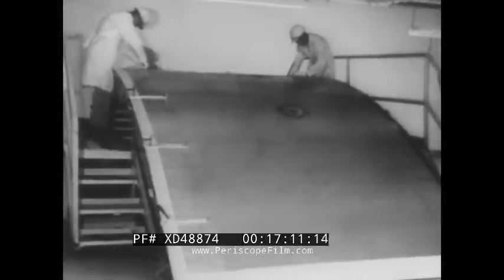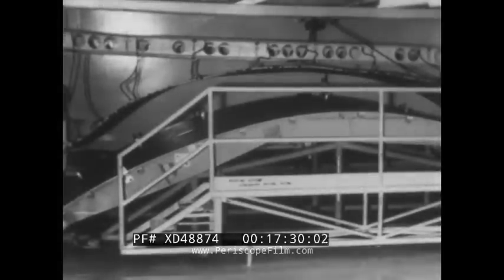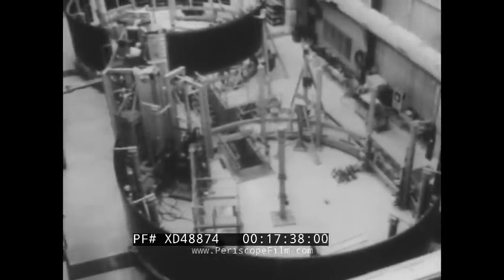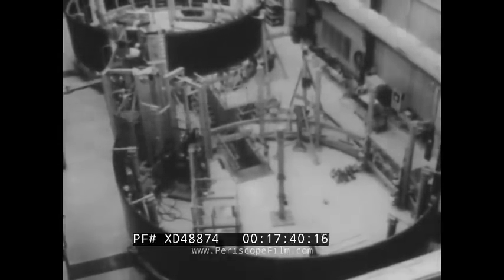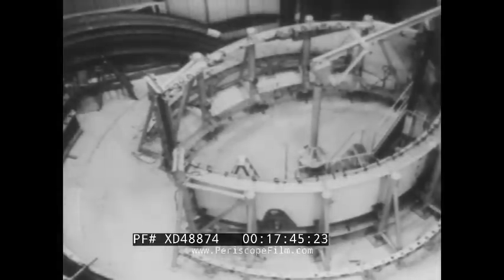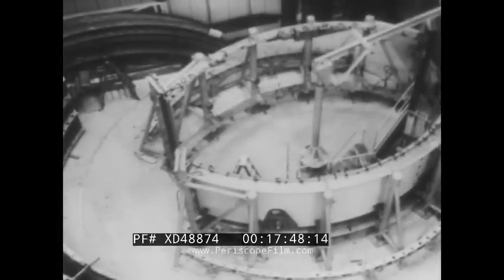Then an adhesive primer is applied, and the panel is oven cured, following which the adhesive is put on. Then the honeycomb is checked over and, if necessary, reworked to make certain that it is filled with isocyanate foam. The panel is then covered with an adhesive bonded fiberglass and then oven cured. And finally, the insulation is bonded to the outside of the panel. The insulation is placed so as to leave the edges of the panel clear. After the panels are welded together to form the cylinders, these edges will be strip sealed.